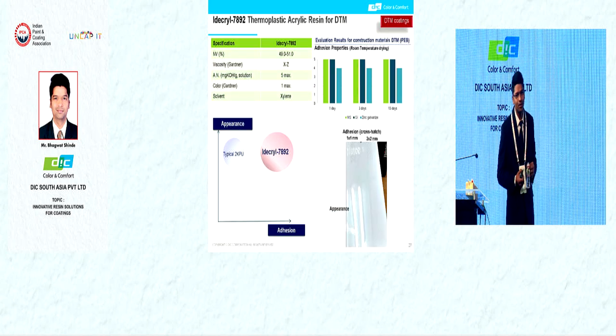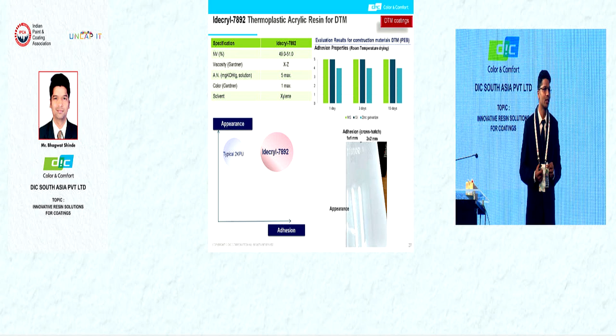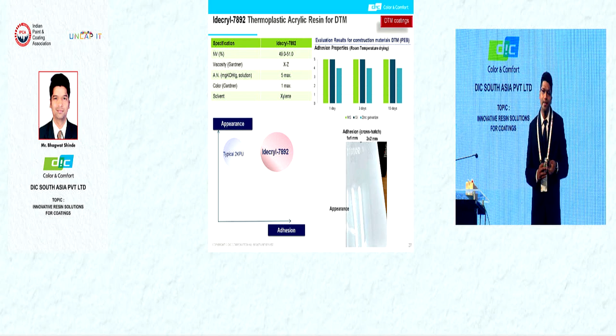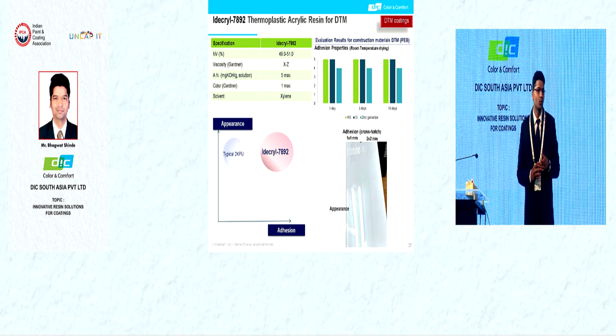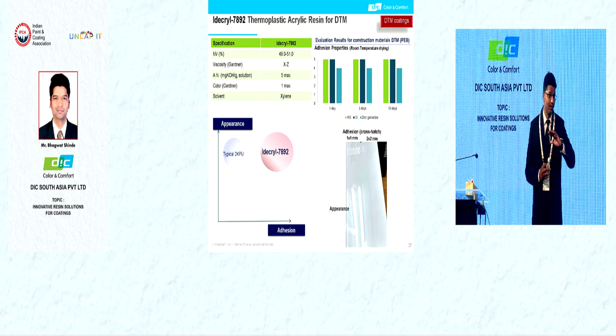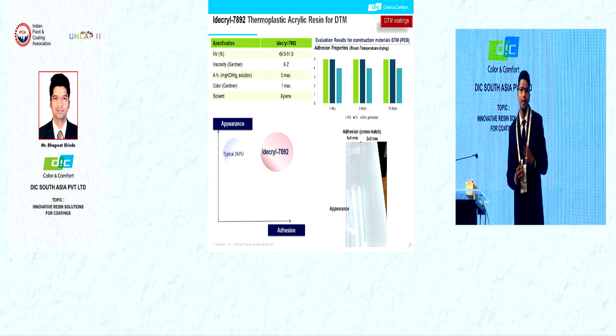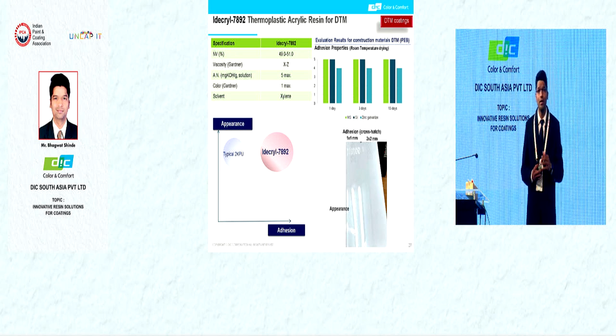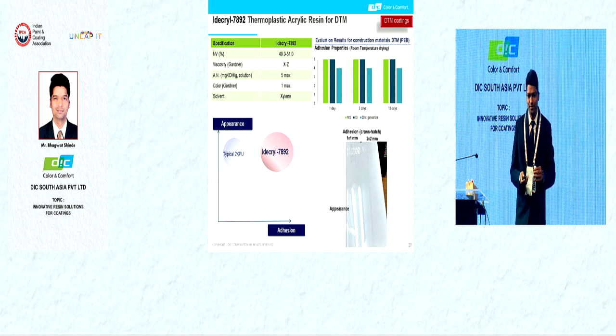Talking about the examples, Idecryl-7892. This is a thermoplastic acrylic resin we recommend for the DTM coatings. This product shows a good adhesion to the substrate, and in DTM coatings, we recommend this product as it does not require any treatment to the substrate. You can use it directly on the metal, and it shows good adhesion, having good gloss. We supply this product at around 50% solids.